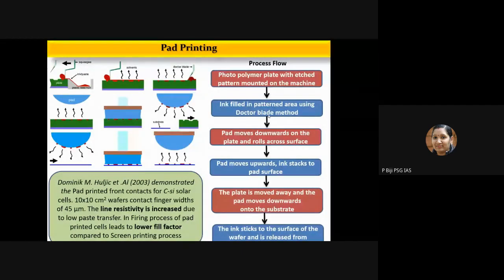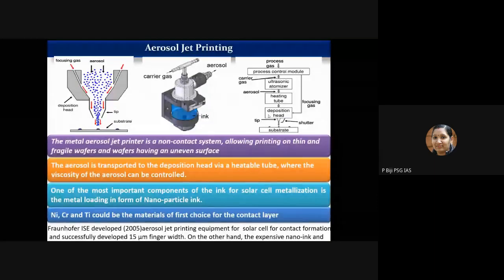Although there are some reports on this pad printing, the line resistivity is increased due to the low paste transfer. Then the firing process of pad printed cells leads to a lower fill factor. Obviously, if the fill factor is lower, you can expect that the performance of the solar cell is not very good. So that was not a widely accepted technology because of that.